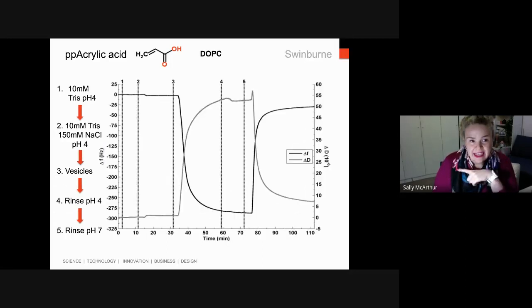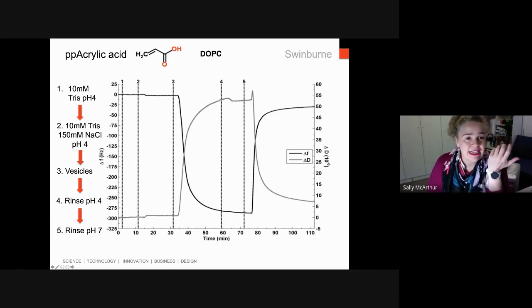If instead we do our system, and you'll notice the frequency scale now has gone from being sub 10 to 325, and our dissipation scale has jumped to a large number as well. So now at stage 1, we're doing the same steps with those buffers. We just introduced some Tris buffer at pH 4. We add the sodium chloride, and you can see a little bit of swelling when we add the sodium chloride at pH 4, but not as much as we saw before.